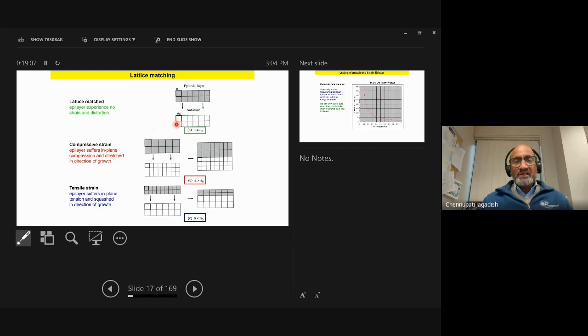And you can see here the substrate has the same lattice constant as that of the epi layer. That means it grows nicely, there's no issue, no dislocation formation or anything of that sort. Whereas if you have a layer which you're depositing that has a large lattice constant with respect to the substrate, then it has to compress itself and distort itself in a tetragonal distortion in order to accommodate the same lattice constant as that of the substrate which you're starting with. It keeps growing, and of course, it doesn't like being distorted, and you exceed the elastic to plastic transition limit, the strain limit. Then what happens is it starts relaxing back to its original lattice constant, and that's where you end up creating dislocations and defects.